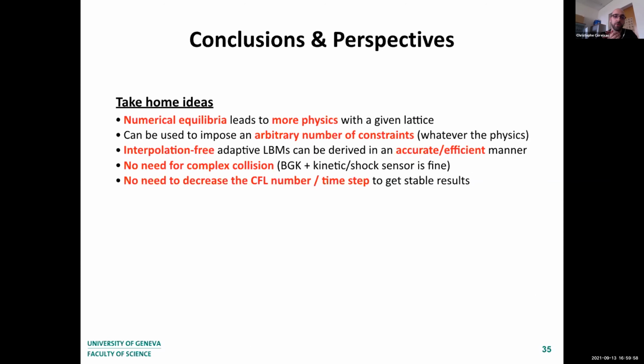So this leads me to the conclusion of this presentation: the use of numerical equilibria allows us to get more physics with a given lattice, because we are able to impose an arbitrary number of constraints, whatever the physics, as long as this number of constraints is smaller than the number of discrete velocities in your lattice. In addition, by working with an interpolation-free adaptive lattice-Boltzmann method, we can end up with a very accurate and efficient lattice-Boltzmann method that does not need complex collision models. Here, we only use a BGK collision model with, when required, a shock sensor technique. And this approach did not need to decrease the CFL number nor the time step in order to get stable results.